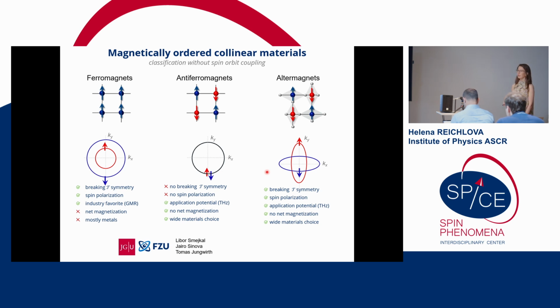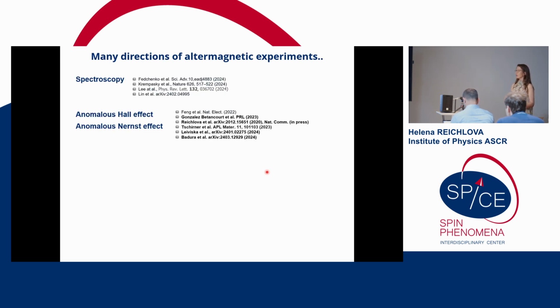But then let's look at some experimental examples. There is now, I would say, almost a boom of experiments on altermagnets. And the most natural way to look at something which has very specific features in the electronic bands is to look at the electronic bands. So angular resolved spectroscopy is the direct evidence, and it now brings a lot of fascinating results. Matthias was showing the work of Juraj Krempasky, where in MnTe we showed that indeed one can observe the calculated alternating splitting of the spins in the momentum space. And it's not the only work. There are also a few other works either on arXiv or already published.